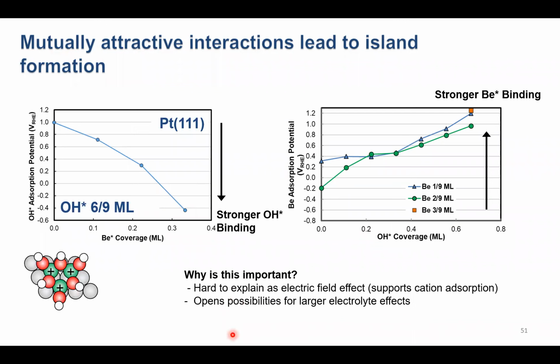And so why is this important? Just briefly, it would be hard to explain these effects as being due to the effect of an electric field. And so it strongly, at least to me, supports that we have this beryllium cation sitting very close to the surface such that it can directly interact with the adsorbed hydroxide to form these beryllium hydroxide islands. And also we could now consider how might this affect electrocatalysis.